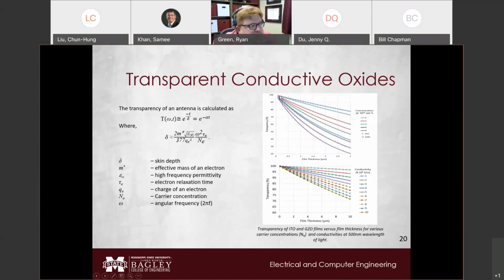So if we take a look at our doping concentration, the more and more that we add of a dopant into this, the less and less conductive, or rather less and less transparent it becomes, as we increase film thickness. And just to show you the relationship between your concentration and your conductivity, here's essentially a conversion between these, basing your transparency off of conductivity. And we find that the more conductive it becomes, the less transparent it becomes.